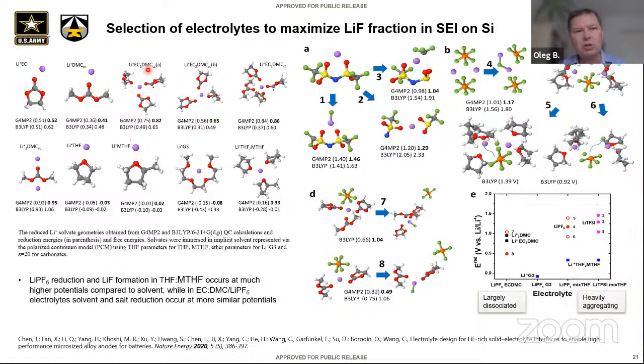So now we can take LiPF6 with these reduction potentials for the solvent, and plot them here. The reduction potential for DMC, this one, is the one where DMC gets reduced. That's with EC, that's a lithium 2, or just with 2 DMC. So my point is that in EC-DMC, reduction potentials for solvents are going to be here, while the majority of the species are largely dissociated. So there are going to be very few of these aggregates, and the more probable species will be something like a contact ion pair of lithium PF6.